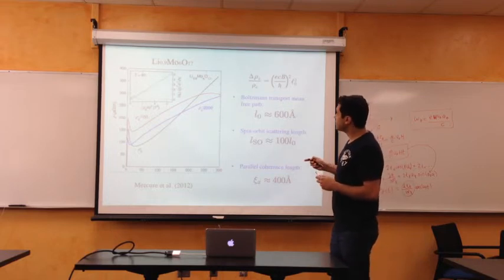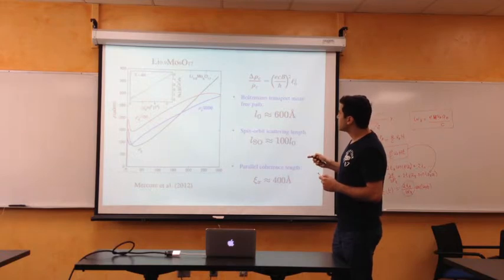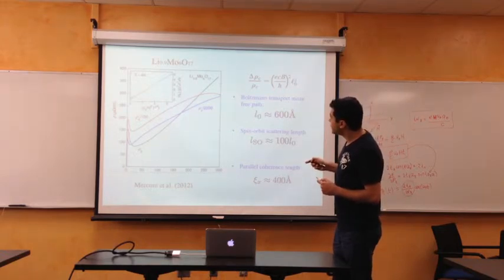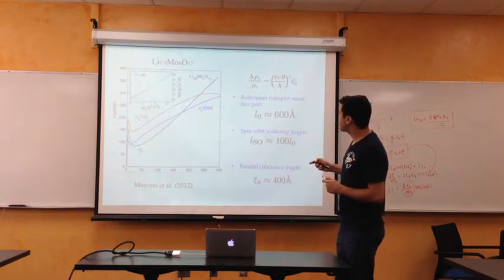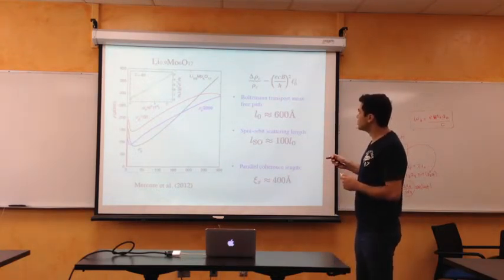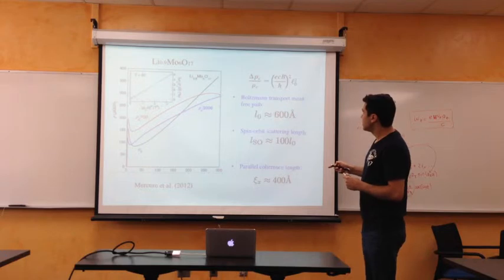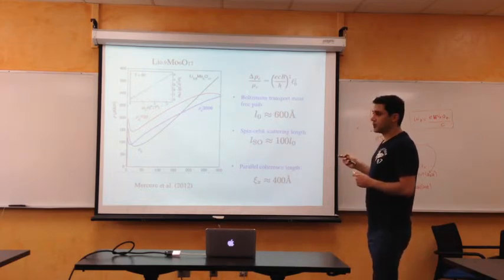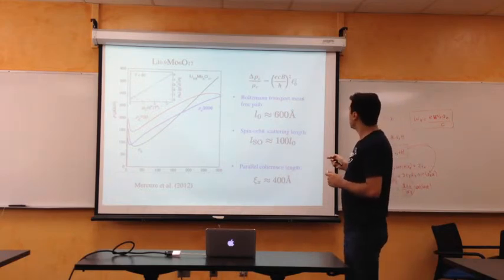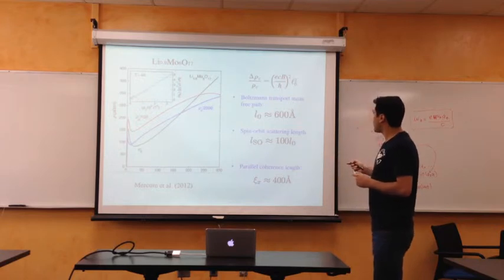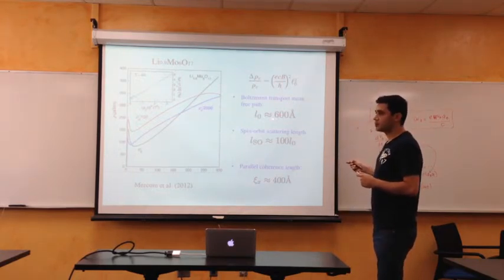This inset here is the magnetoresistance, and it shows a quadratic behavior with the applied magnetic field. Now this is important because the slope of this curve, from the Boltzmann transport equation, can give us the mean free path. We can estimate it to be about 600 angstroms.